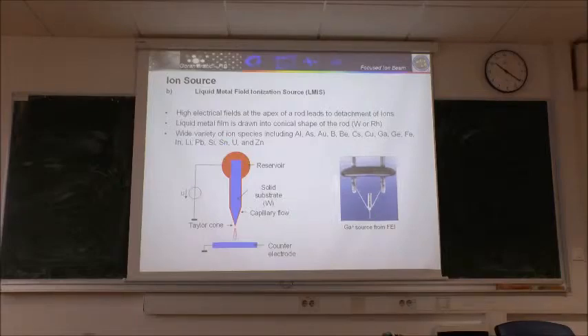And this is the basic idea of the source. You have very sharp tip. At the end, it's so-called, physicists would maybe know better, so-called Taylor cone. And at the end, you apply some voltage, high voltage, in the range of 1 to 10 kilovolts. And those atoms at the top of this cone are ionized. They lose electrons, they become gallium plus, and you just accelerate those ions down to the column. And this is a practical ion source from FEI. The lifetime of such ion source is somewhere around 1,000 hours, 1,200 hours. So if you use extensively this machine, it should be changed twice per year, for instance, so once to twice per year.